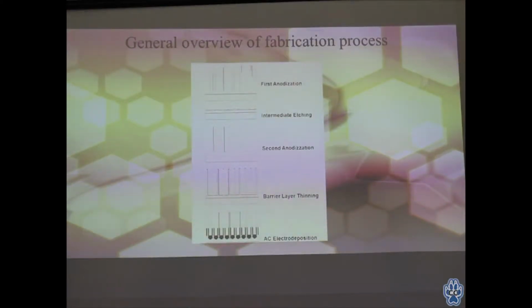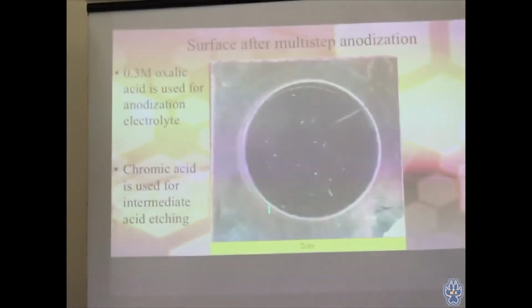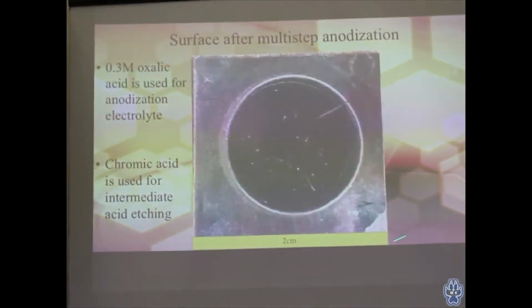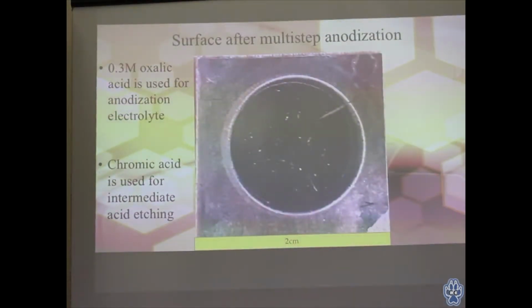After we are happy with the order of our samples, we then would move into the barrier layer thinning process. And then when we are happy with the increase in diameter size and decrease in resistance of the samples, we would deposit the nickel using that alternating current pulse. This is an example image of what the surface of this aluminum would look like after the multi-step anodization. It's on a 2 centimeter by 2 centimeter aluminum sheet, and the aluminum is extremely pure, 99.9996% pure aluminum. We use a 0.3 molar oxalic acid, which is an organic acid, for our anodization electrolyte, and we use chromic acid as our intermediate acid etching agent.